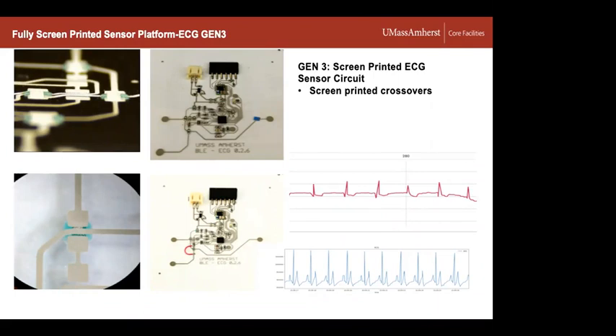And so these are what I talked about as far as design rules. Once you can start going to crossovers and then possibly vias that go through to another printed circuit pattern on the opposing side of the substrate, now you can start to compact these, get more sophisticated circuits and printed circuits, and look at even more complex systems. And all of these are basically systems. You have sensors, you have analog data acquisition components, you have computational components, and you have some type of a data transmission, wireless transmission component. So they can get pretty sophisticated very quickly. And the problem is you need to integrate matching and other surface mount components with this system along the way. And so what we found is that we can handle many of those elements using the automated pick and place tool and further enhance the ability to fabricate and assemble these without a lot of manual effort.